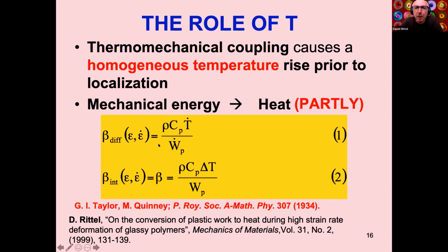So what happens with the integral? Well, by the first law of thermodynamics, you cannot generate more heat than you invest work. So this has to be smaller or equal to 1, and that makes sense. Okay, but the differential is a time shot. It's in fact a series of time shots of the process, and you can show and you can measure that at some stages this ratio exceeds 1. This ratio can exceed 1 without violating the first law of thermodynamics. But on the closed cycle, in the integral sense, you will never exceed 1, unless, of course, you have extraneous sources, and I won't elaborate.